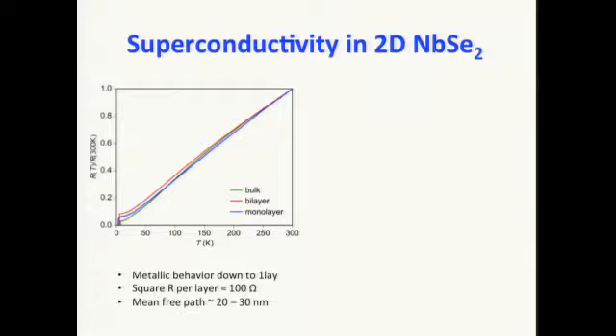in the monolayer material. Some characteristic about the device, it's about the square resistance per layer, it's about 100 ohm, corresponding to some mean-free path about 20 to 30 nanometer in this case. And the coherence length of the superconductor is about 10 nanometer, so we are sort of in the clean limit in this case, even down to the atomically thin limit.